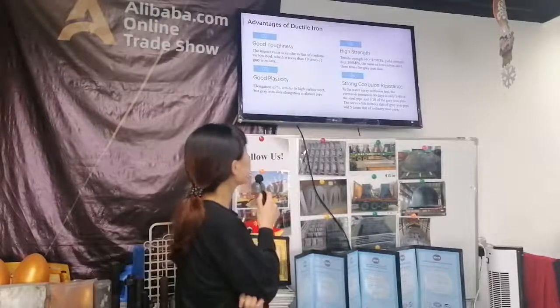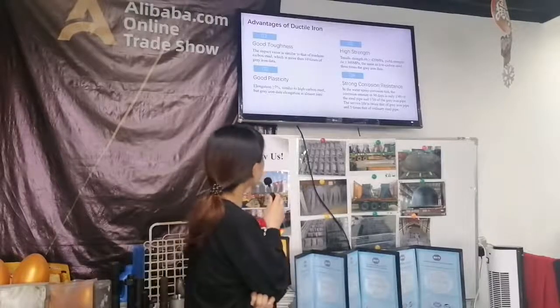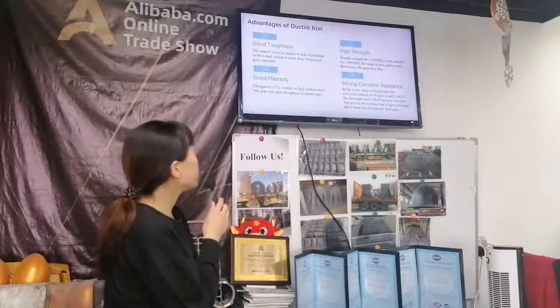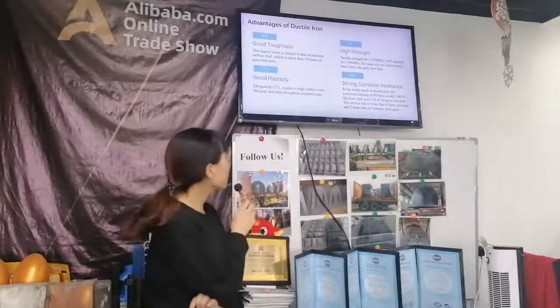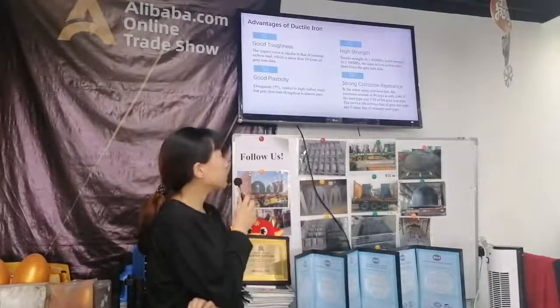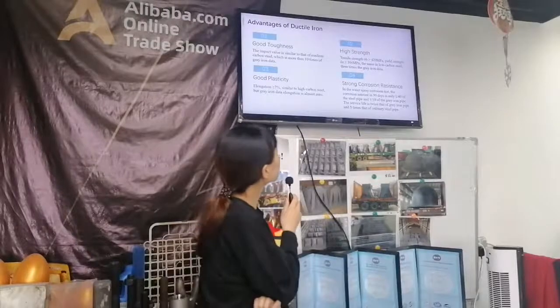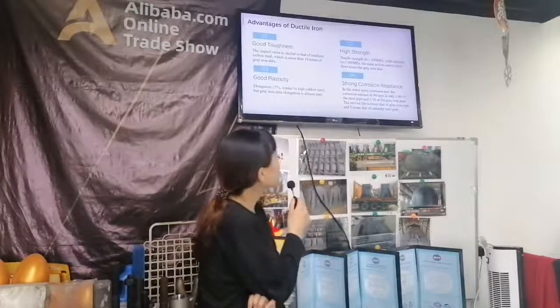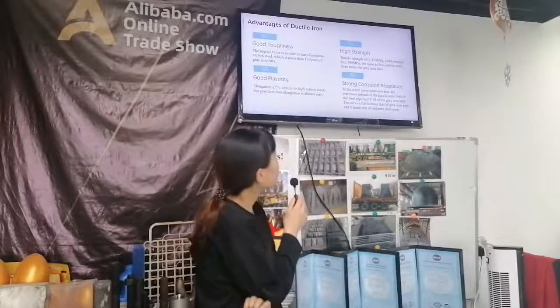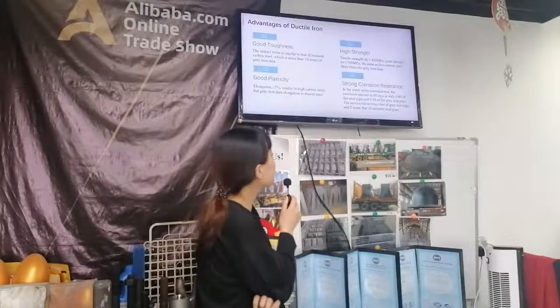The first one is toughness. The impact value is similar to that of medium carbon steel, which is more than 10 times that of gray iron. Second, it's high strength. Tensile strength of 420 MPa, yield strength of 300 MPa, the same as low alloy steel, 3 times that of gray iron.